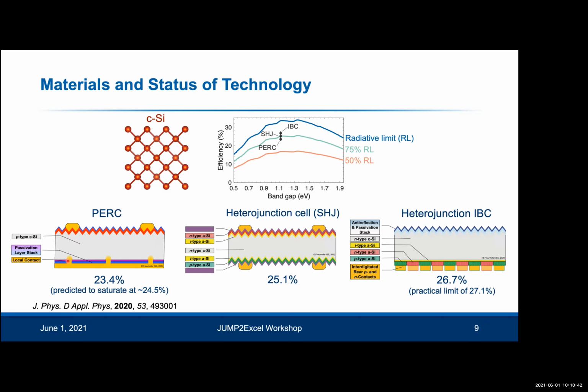And you only have small holes milled, etched into that, where you have the local contact for extracting holes from the p-type silicon layer. Currently the state-of-the-art efficiency for these PERC devices is 23.4%, but in the future, this is predicted to saturate at 24.5%.